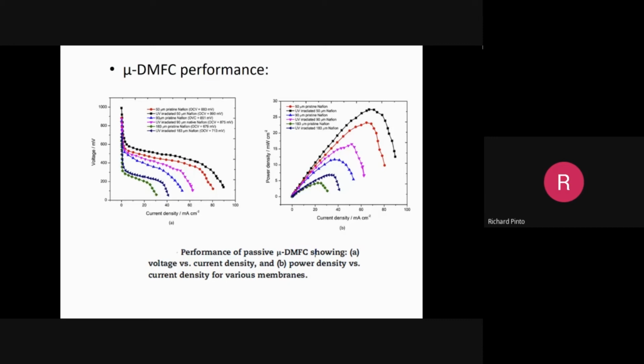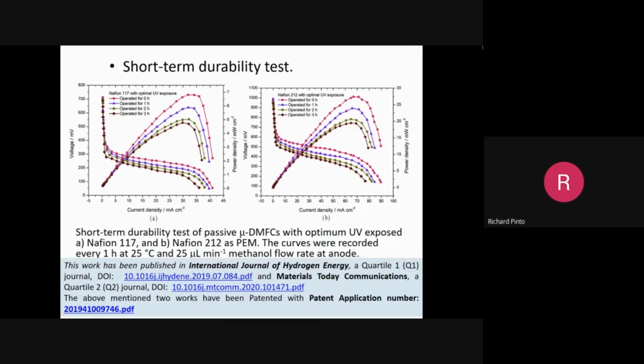This is the optimum exposed. This is UV exposed 90 micron, this is 183 micron. Best performance obtained, of course, with 50 micron. So there is significant increase in the power density of the irradiated Nafion. So this is an important finding, and which we have, of course, published and patented earlier.